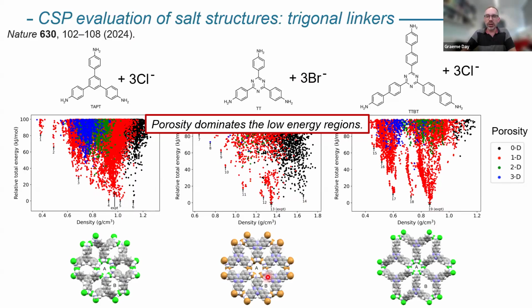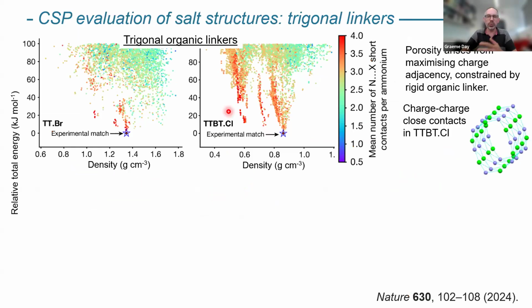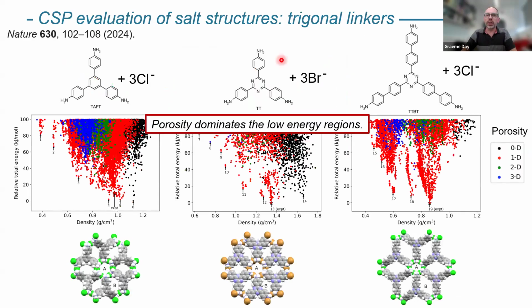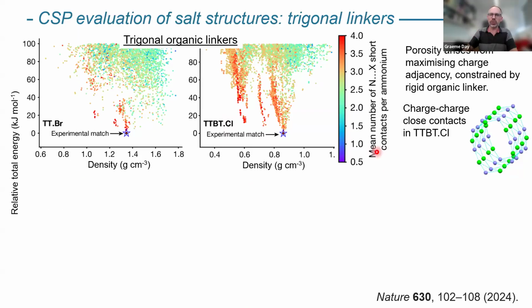And so this got us to a set of useful materials. We did some more digging into these because we want to be always learning more about the next sets of structure we might go and make. In this case, again, focusing on electrostatics, we looked at how frequently does the anion get close to the cationic group on these molecules. So sort of counts of close contacts. What you find is all the low energy porous structures get there because they can really maximize the number of those close electrostatic contacts between our charged groups in these systems.